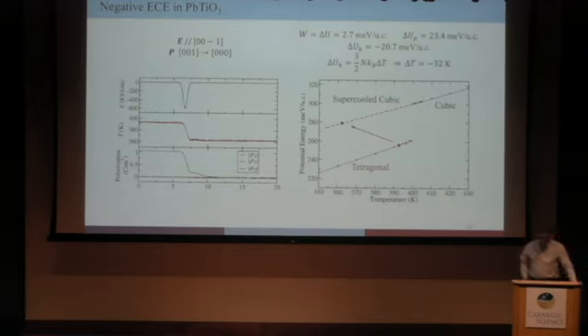Okay, and then finally, if you look at lead titanate, we know lead titanate has a much higher TC and a much larger latent heat. All these phenomena apply rather similarly, but the energy scale is just significantly larger. So here we exhibit a different case. This is just for exercising the ideas. Here we apply an electric field that's anti-parallel, but it's timed to be short enough that it doesn't allow the polarization to follow. So the electric field is zero, and then we have an anti-parallel electric field for a short time, and then it turns off again.